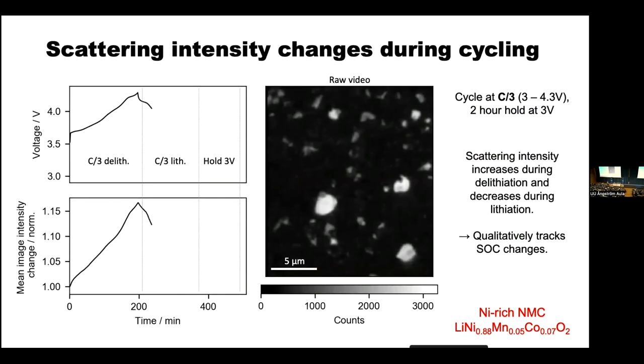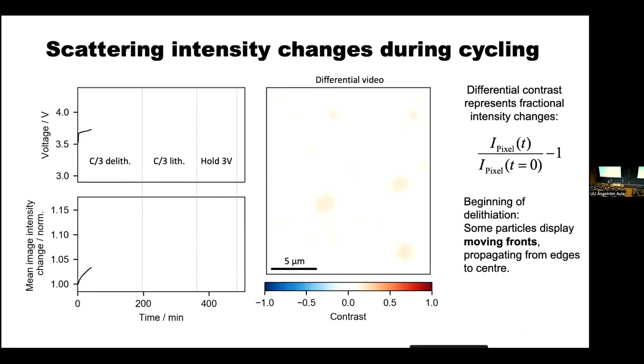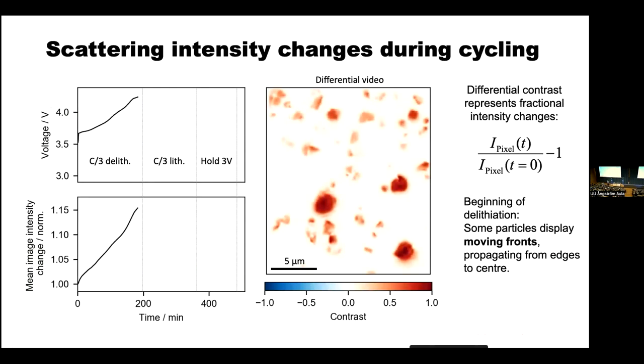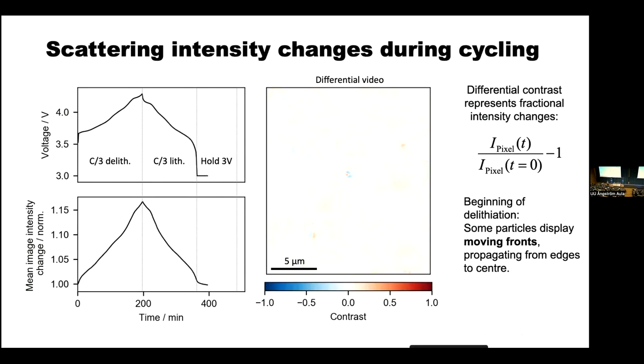And so what you're looking at is now a whole field of view. We've come back out of lockdown, we've improved our setup so we can now look at multiple particles at the same time. This is again looking at the basal plane of an NMC particle, and you can see things are happening. So let's dig down and see what's actually happening at the individual particle. We'll do something called a differential image, which is the image at one point, and then you subtract the initial point from the time point you're interested in, which gives you a much better contrast.